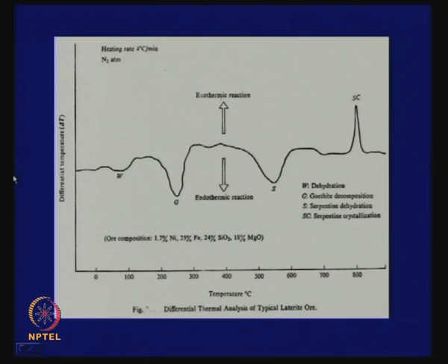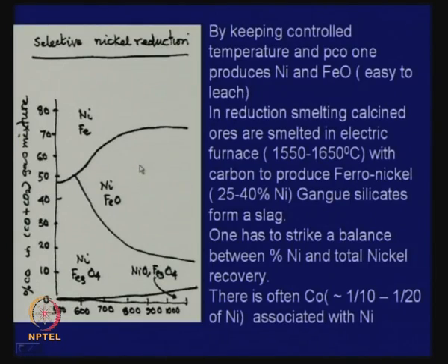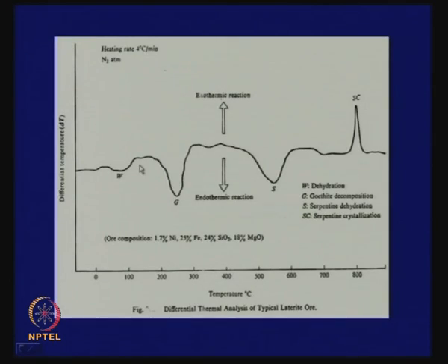The small endothermic peak at W, which is at about 100 degrees, is due to evolution of a small amount of water from an already dried sample. It has been dried, sun dried, there is some moisture still left. The ore from the mines contains a lot of water, some as moisture, some in combined form. We have to remove that also. So, the first endothermic peak shows endothermic evolution of water, it absorbs heat.